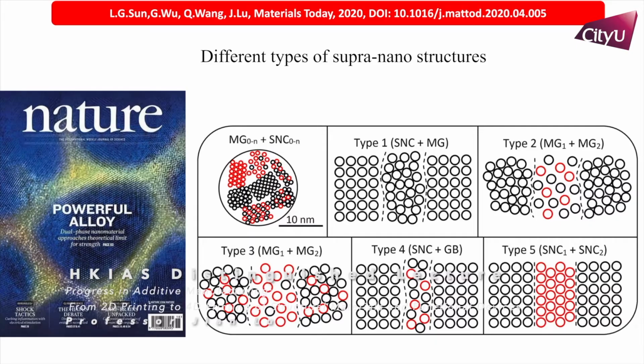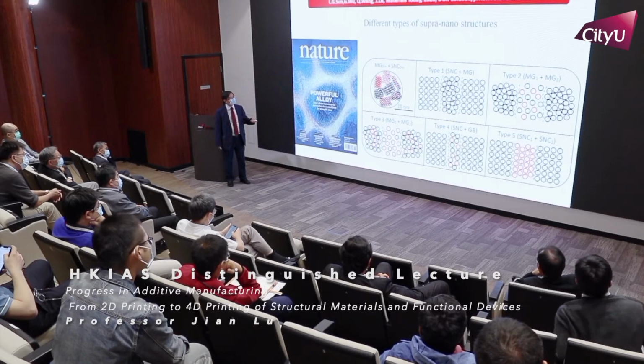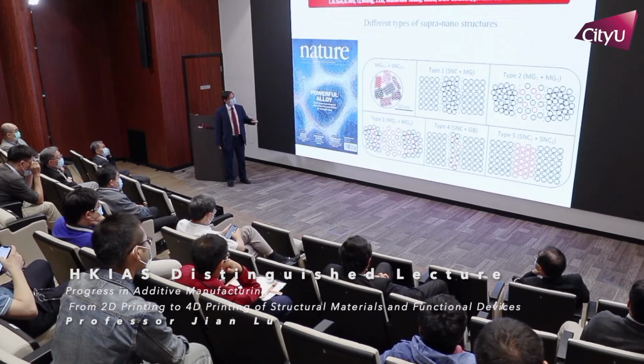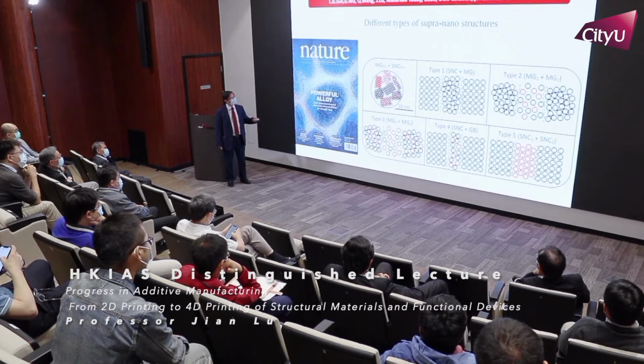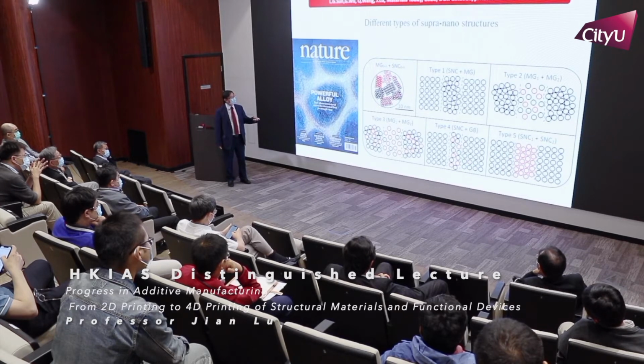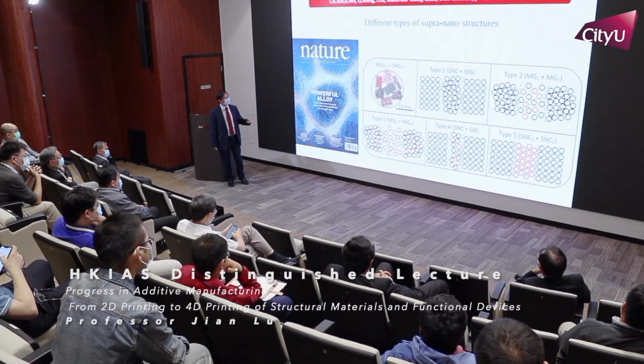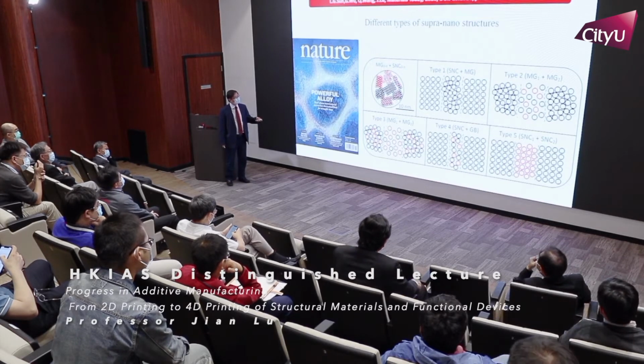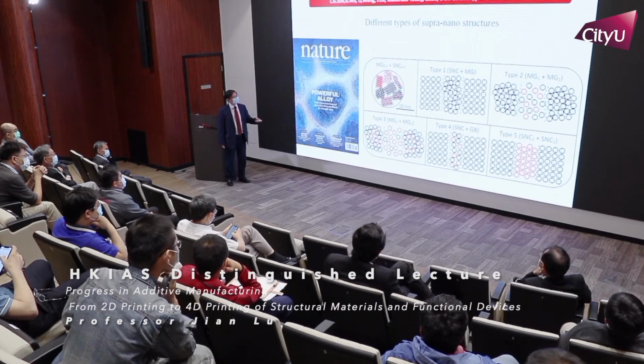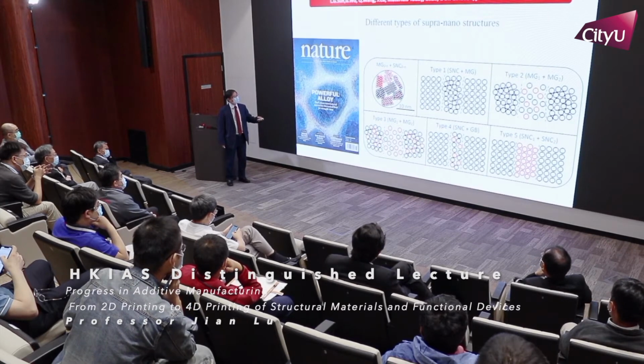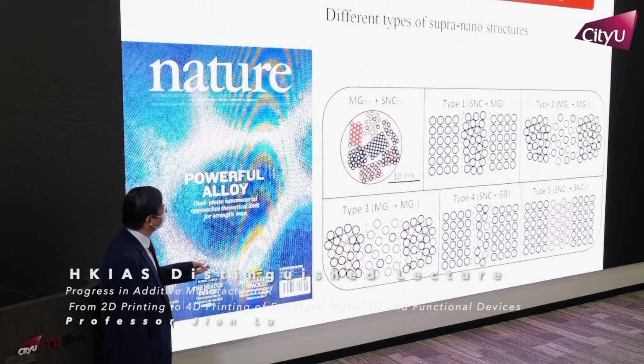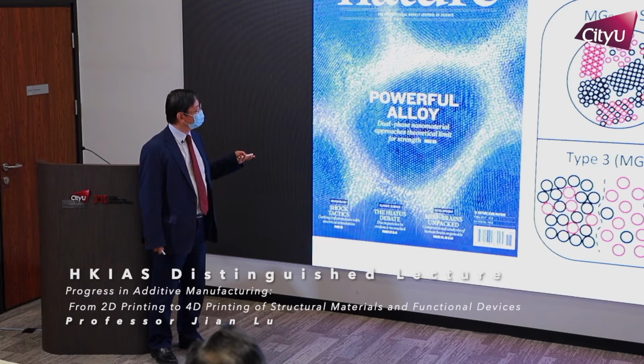So at the beginning, we tried to produce this supra-nano structure with a two-phase metallic glass mixture. We try to obtain a material with nanocrystal and metallic glass. But it's quite difficult to produce, because when you have two phases with the same composition, either it becomes nanocrystal, or it remains metallic glass. Then we designed a process, and we observed that if we can manage the composition properly, we can obtain this structure.